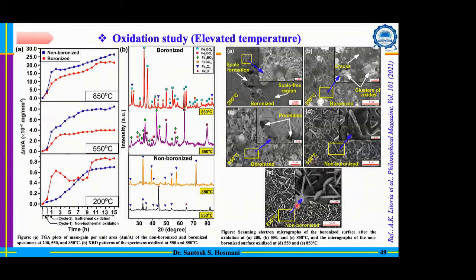Now at elevated temperature also, we have observed excellent results. You can see here, on the left-hand side, the red one is basically the TGA result for the boronized surface, and the blue one, the square dot, is for the non-boronized. You can see that the red is always on the lower side compared to the blue one. That means you have very good oxidation resistance for the boronized surface. Now, why is that so?